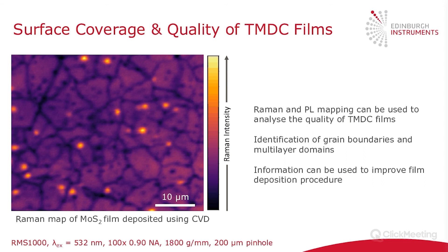You can also extend this to a much wider area. Looking at a continuous film of molybdenum sulfide deposited using chemical vapour deposition, a Raman intensity map can be used to analyze the quality of the film. Bright spots suggest multilayer molybdenum sulfide, and you can also clearly see the grain boundaries. This gives an indication of how good your film is and whether you need to improve your deposition procedure. Next year, a webinar will be dedicated solely to analyzing 2D materials using photoluminescence and Raman in more detail.